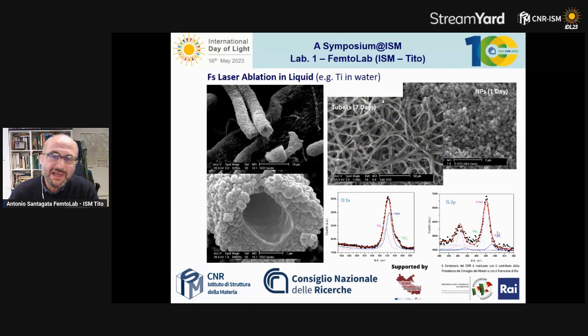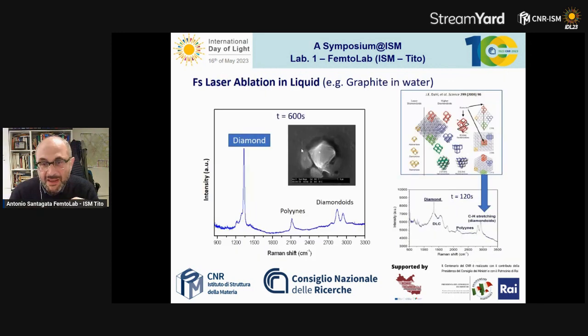In this case, we have obtained in liquid the ablation of titanium, which after a few days from nanoparticles, we have the formation of microtubes by self-assembly of them. And actually, the mechanism is induced by the presence of titanium hydroxide. And as well, because of the high temperatures and high pressures involved in the process, we can even perform the colloidal formation of our nanodiamonds.